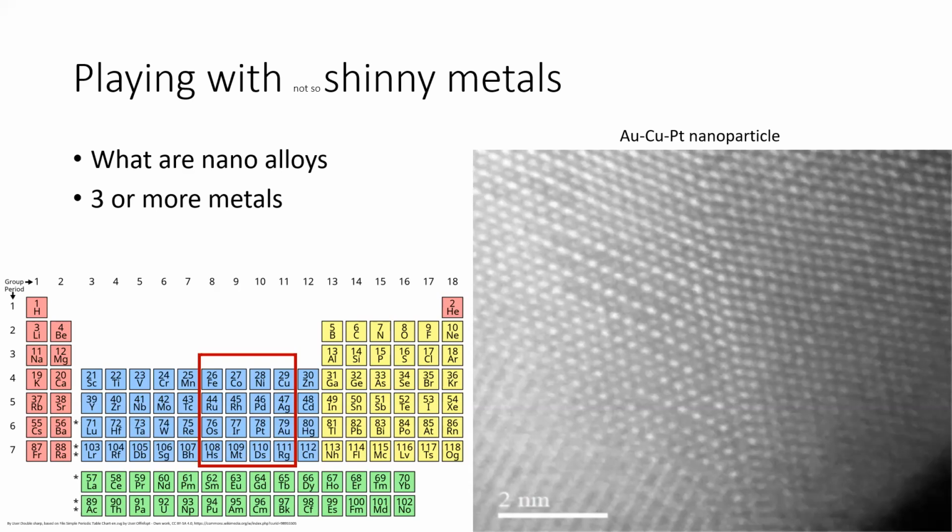Platinum is going to have a different bonding length between platinum and copper, and as you add another element in there, that bonding length is going to be different. So that perfect, say, cubic crystal structure is now going to be distorted in one way or another as those different elements are in there. And so it's just a matter of trying to find that in the entire crystal structure as it moves out.